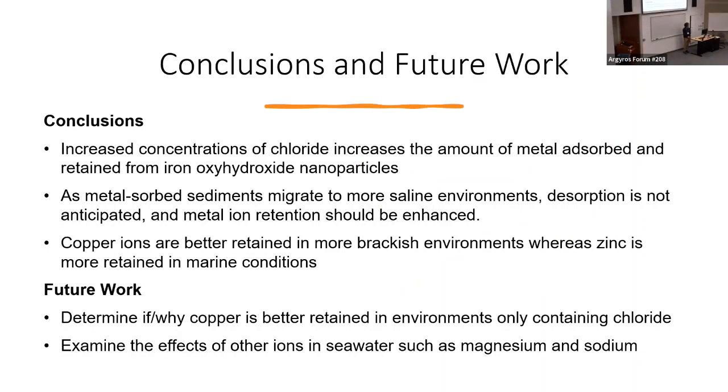And to get into the conclusions, we see that increased concentrations of chloride increased the amount of metal that was adsorbed and retained by the nanoparticles. In a more practical sense, if we were to migrate to more saline environments, such as the ocean, desorption is not anticipated and metal ion retention should be enhanced. And then copper ions are better retained in brackish environments, whereas zinc is more retained in marine environments.